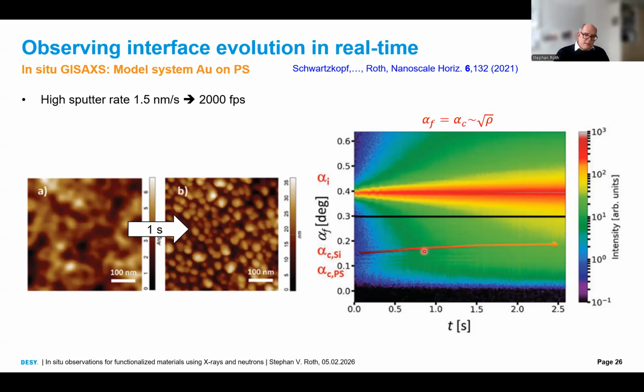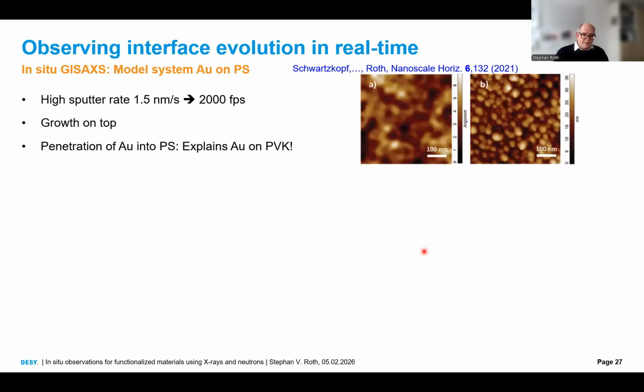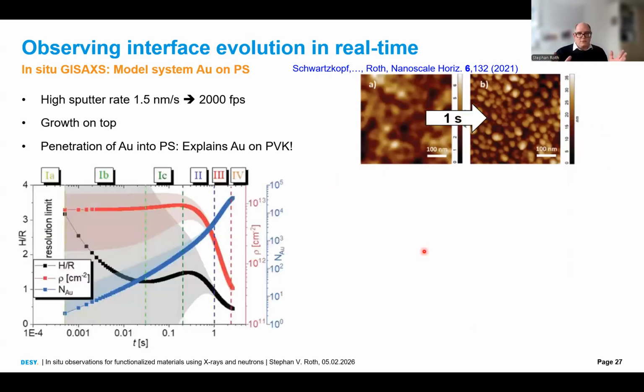And actually, we look again at these density changes, and what we find is, first, we make a normal analysis of the clusters. We see here how many gold atoms are in a cluster. We can detect from 2 atoms up to 10,000 atoms per cluster. We follow the cluster density, and we follow the aspect ratio. For example, we found out that if you put only 2 gold atoms on top of each other, they are really on top. They are like a molecule standing like this, and only with more gold atoms incoming, they are flattening.